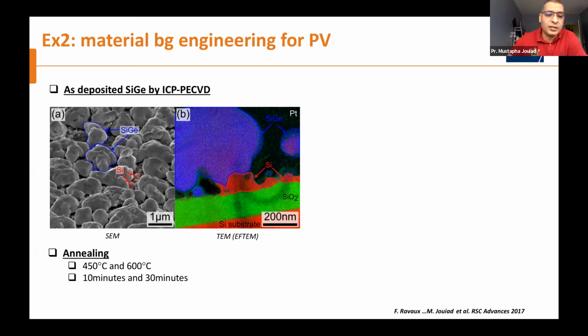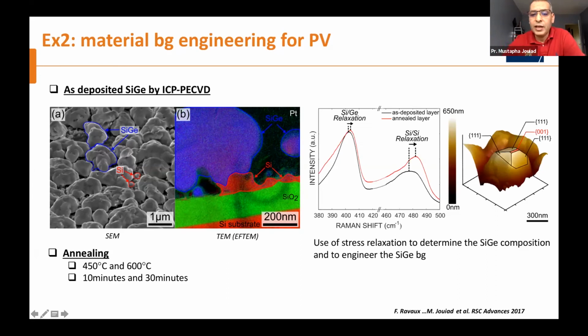So what we did, this is as-fabricated silicon germanium, and then we did the heat treatment. When you fabricate silicon germanium, silicon and germanium have a huge mismatch. So we start with a seed of silicon, then go slowly, gradually, until we obtain the silicon germanium. And when we do heat treatment, we release the stress inside this composite. Using this stress release, we were able to lead to different compositions.